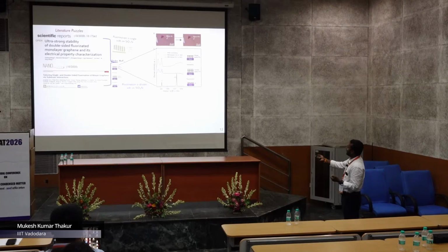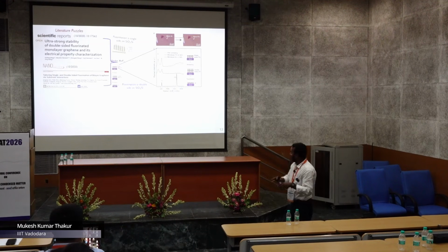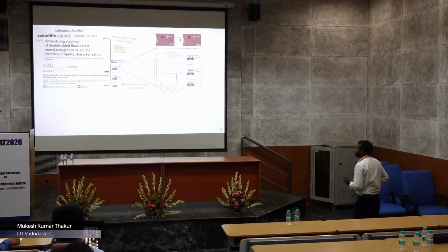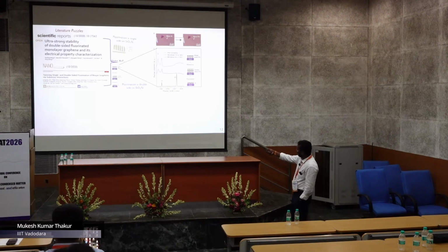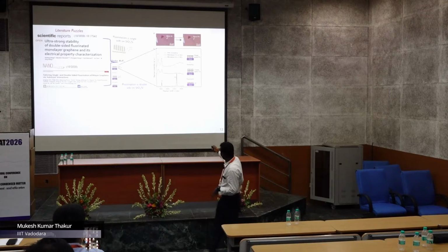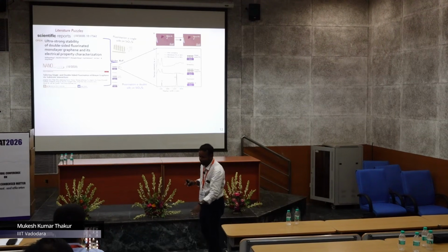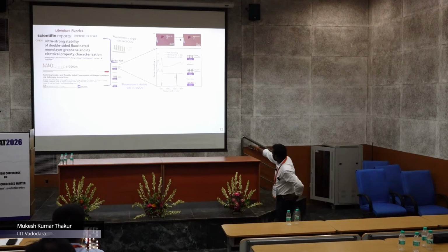So basically, fluorine is not going anywhere. So still we have this heterostructure. So the puzzle was this. What was the problem about this? He said, okay, when you have monolayer fluorinated graphene, this is the graphene without defect. When you heat this at 300 or 400, this D band will decrease because fluorine is going. When fluorine goes, D band will decrease, and the G and 2D modes will increase. So he was saying this, but this is saying no, it's not true.